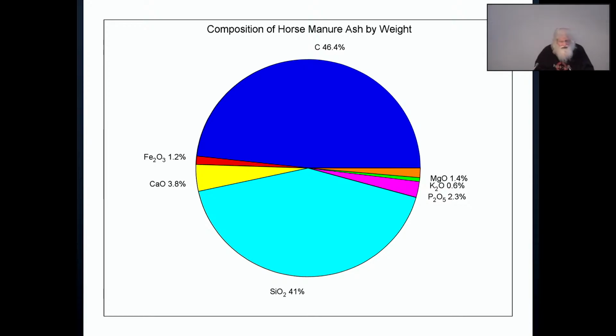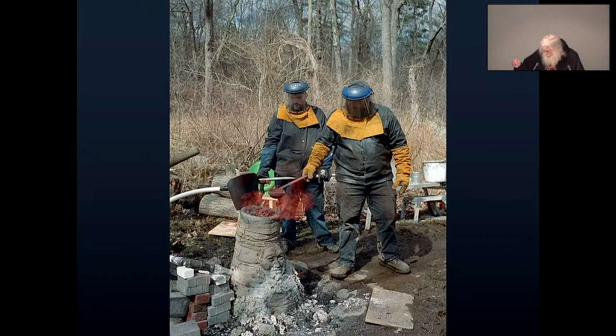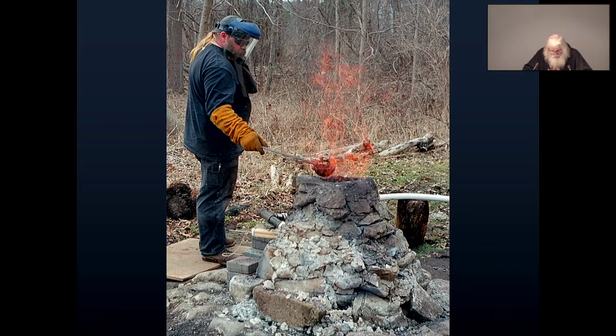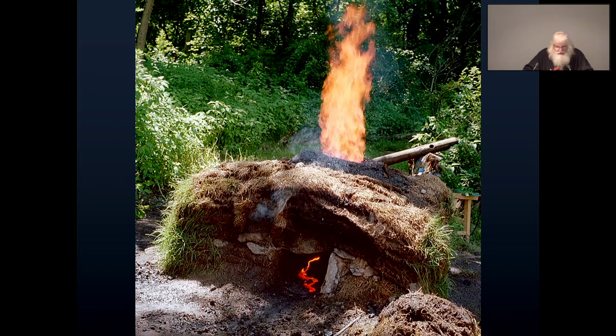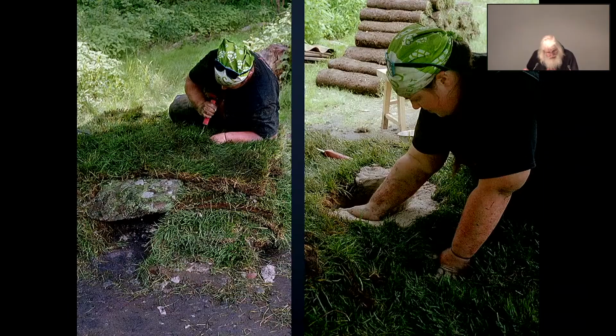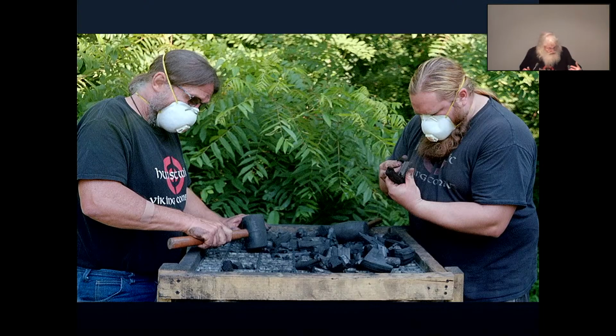Then back home in the United States, we started doing many, many smelting experiments with our own ovens. And we used a lot of different kinds of ovens. We used clay ovens, and these were used in Scandinavia using high temperature clays that were available there. We used stone ovens. There's some evidence that ovens were made out of stone. And we used turf ovens because the evidence suggests that here in Iceland, ovens were made with turf with only a thin clay liner inside to protect the turf from the heat. And we developed our skills, so our skill in making ovens, our skill in processing the raw material.